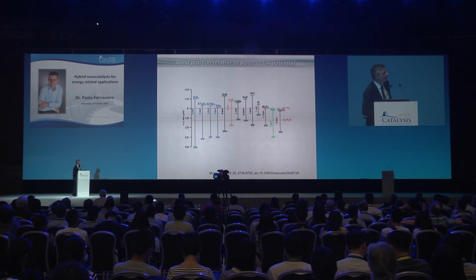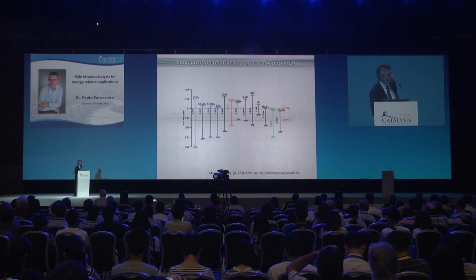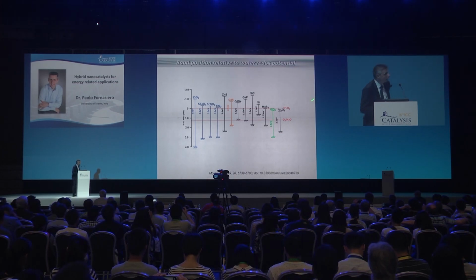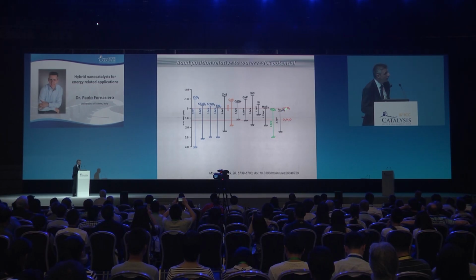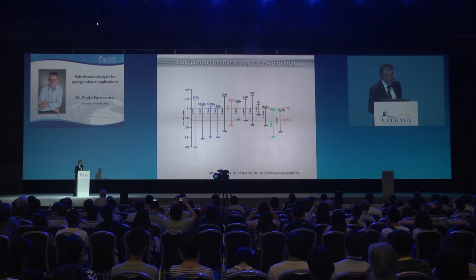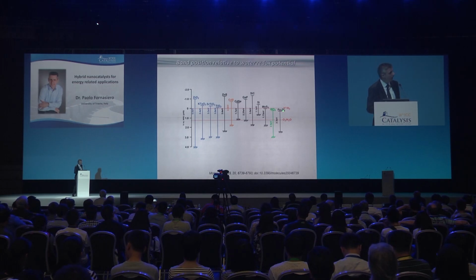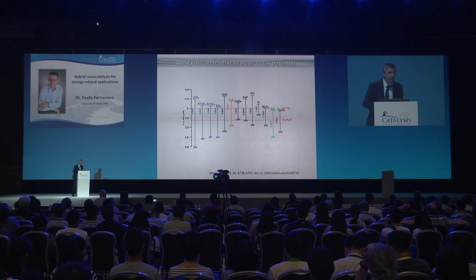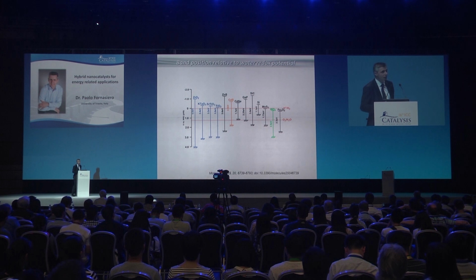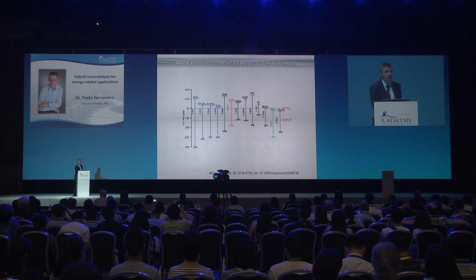So let's start from the first example, which is iron oxide. Iron oxide should not work, as the position of the conduction band is below the energy requirement for proton to hydrogen reduction. But we know that in nanocrystals, if you go nano, you can increase the band gap and you can raise the position of this conduction band. And as nicely shown by Emily Carter from Princeton,